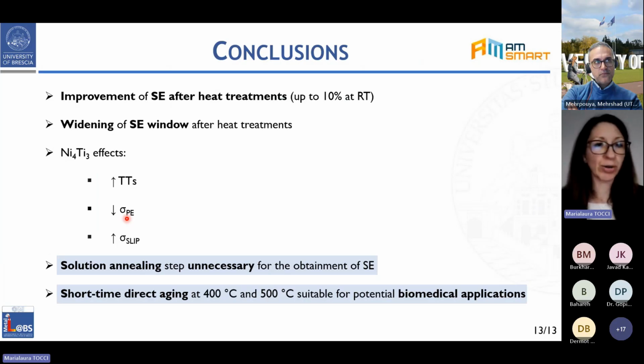So, to conclude, we have an improvement of the superelastic behavior after all the heat treatments carried out. This was demonstrated by the widening of the superelastic window after heat treatments in the temperature range that is of interest for biomedical application. This is mainly due to the formation of these Ni4Ti3 precipitates that, as we can see, contribute in different ways to this enhancement of the superelastic behavior.